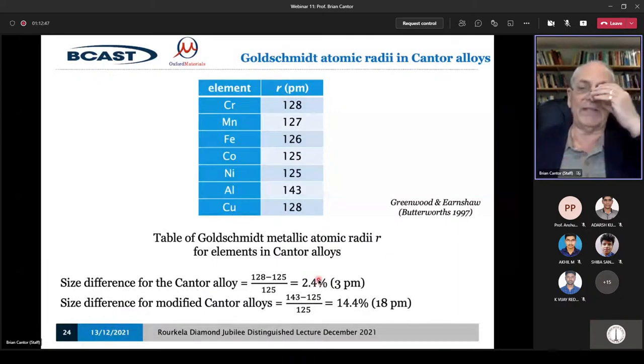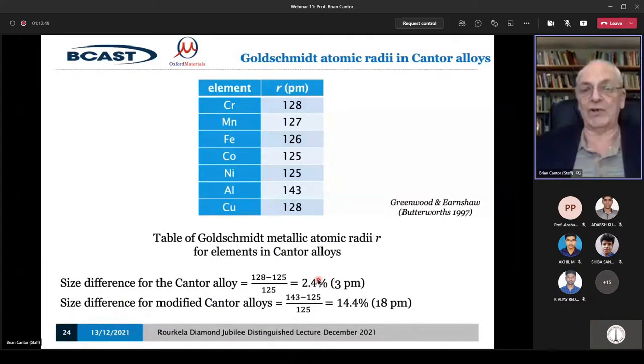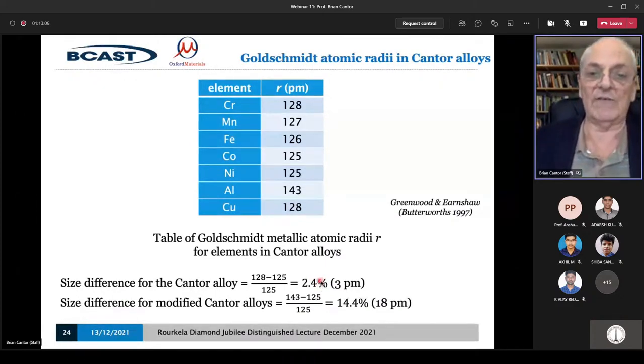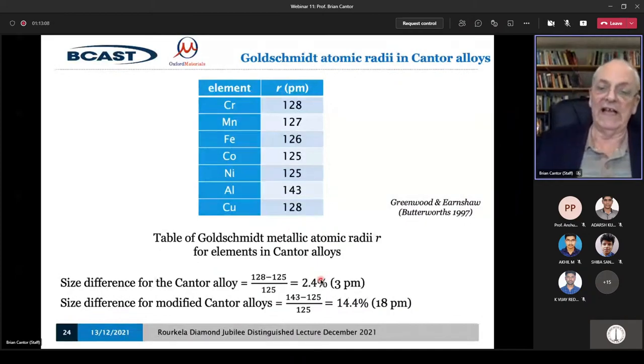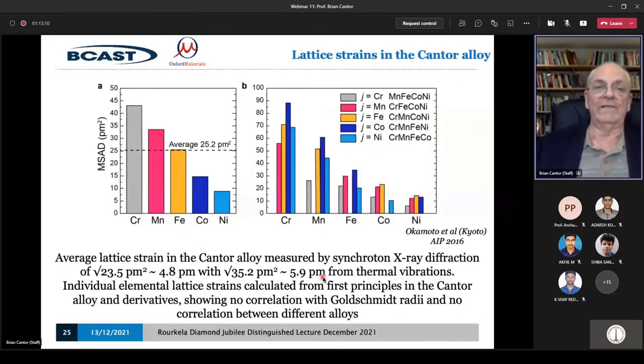By the way, 2.5% is a lot. If you strain any material in bulk by 2.5%, it usually fractures if it's ceramic and begins to deform significantly if it's a metal. They don't strain that much easily. So it's quite a big effect. It has a big effect on the properties if you have even 1% strain. Anyway, let's look at if it's true, first of all.